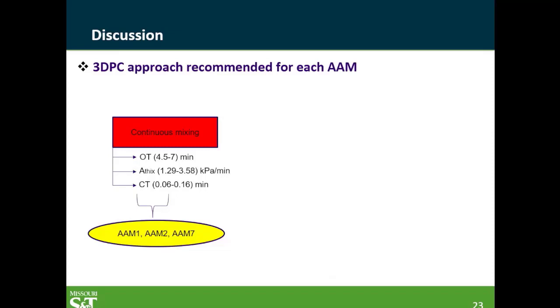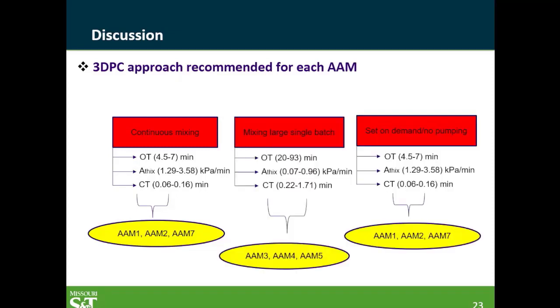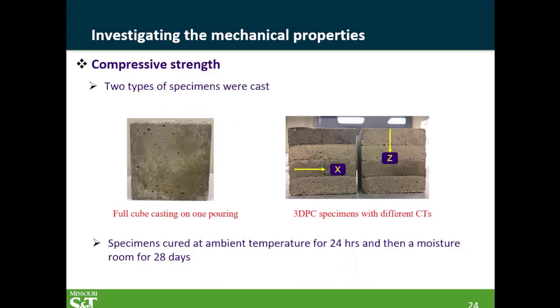And then next, based on this, we end up proposing, as I mentioned, that we have different mixtures. For example, if you have continuous mixing, you can look at those 3 mixtures. And if you have long single batch mixing, you have other mixtures and so on. So based on the characteristics here, we start to tailor different mixtures for different printing procedures. Once we are done with the fresh properties, extrusibility, buildability, all of that, we start looking at the mechanical properties.